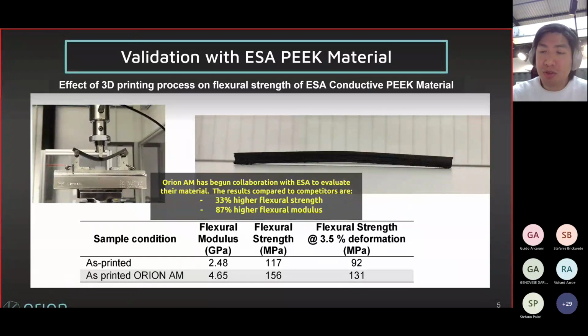We've focused on a lot of different applications, but one of the application areas that we focus a lot on is space applications, and we've also worked with the European Space Agency to validate our process with a special material that they came up with. This is a material that is based on PEEK, so polyether ether ketone. It's the strongest plastic in the world. They added carbon nanotubes and graphene platelets to this material to create a conductive material for space applications specifically. They've been going through a lot of validation of this material, but they wanted to see what we could do with our process to improve the mechanical properties of this material.